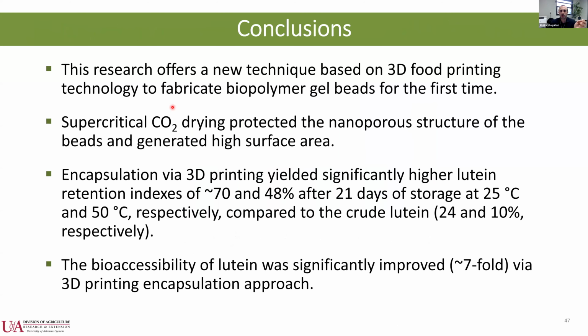So overall, so far, I think we are able to show, maybe for the first time, that 3D printing can create biopolymer gel beads. CO2 can really protect the nanopore structure during drying and creates high surface area, and encapsulation of lutein into ethyl cellulose and zein matrix along with starch gel significantly improved the chemical stability. In this case, we are seeing improvement from, let's say, 24 to 70%. At 50 degrees, we are seeing an increase from 10% to 48% retention after 21 days. And the bioaccessibility was also improved about 7-fold when you use zein, especially as the core material during 3D printing.